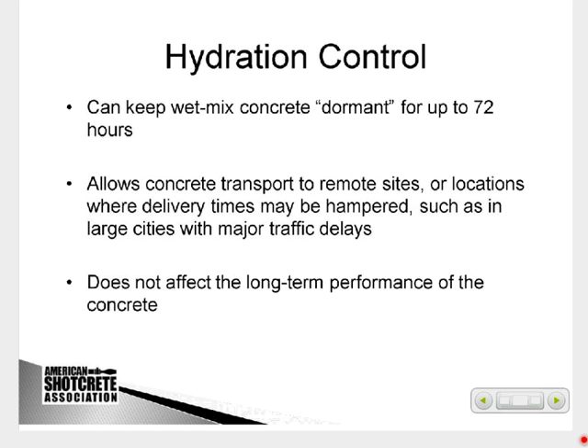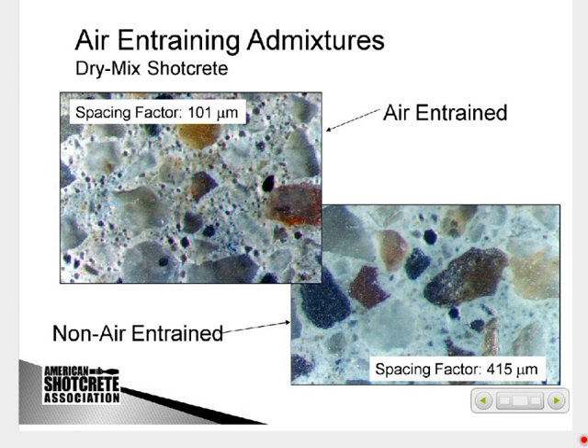We also do use hydration control. This allows the concrete and wet mix to go dormant so it doesn't hydrate, doesn't start to set up, and it can go as long as 72 hours. This has been used in tunnel works where they pump maybe a mile or 2 miles underground, as well as areas where delivery times can be affected. And it does not affect the long-term performance of the concrete.